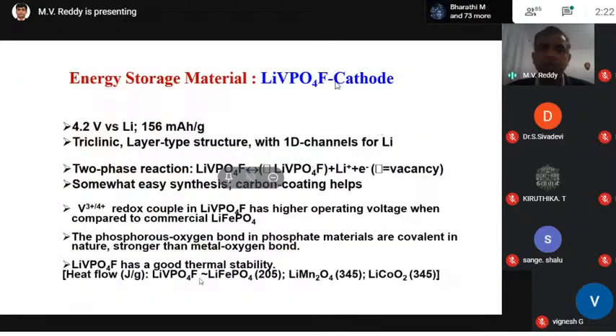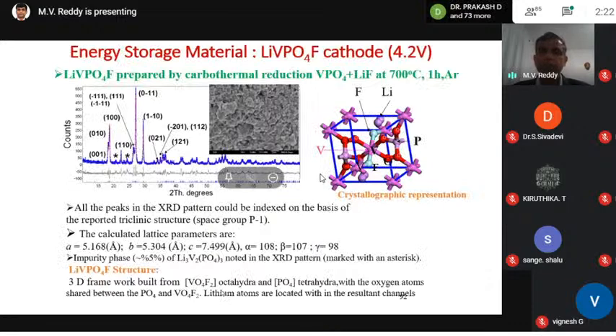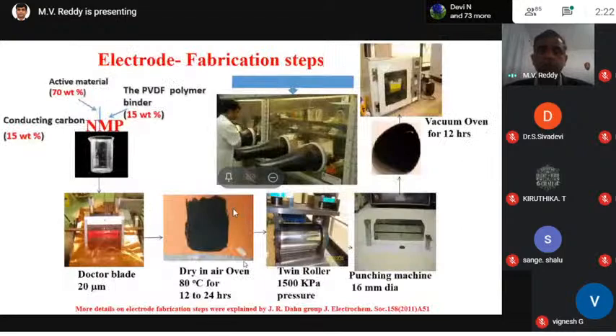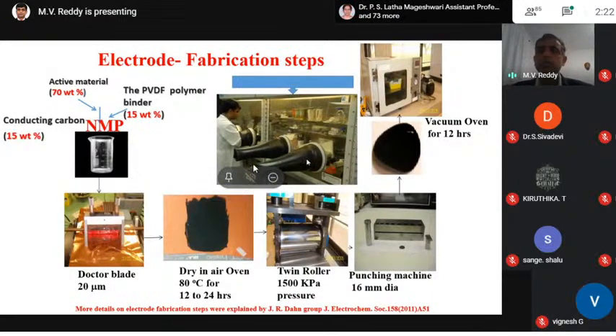If you talk about lithium vanadium fluorophosphate, we try to prepare the sample. Again, here is the vanadium 3 plus to 4 plus redox couple and reasonably good thermal stability. These are the samples prepared by the carbothermal reduction method. I'm going to skip the details. So for the electrode fabrication, 70, 15, 15, and finally I coated it on copper or aluminum foil, twin rolled it, used a punching machine, and finally we can use this dry electrode in the glove box.